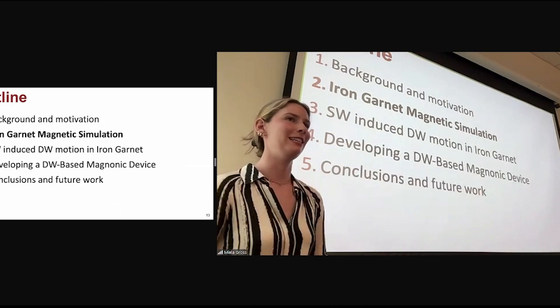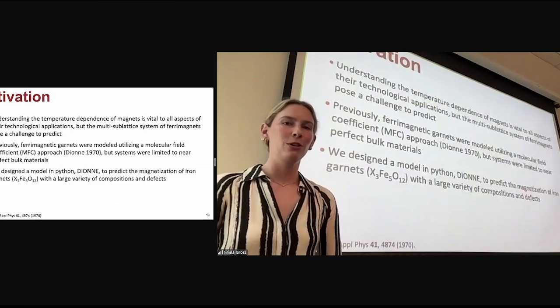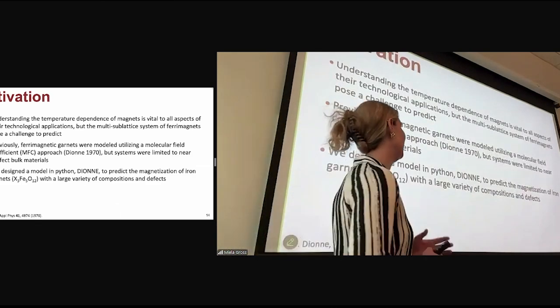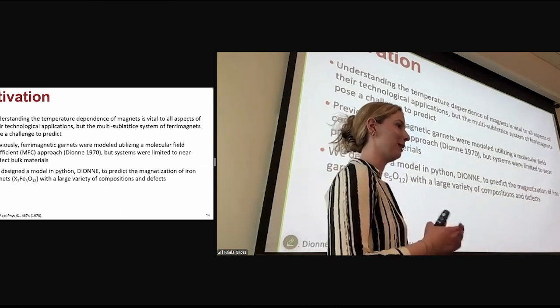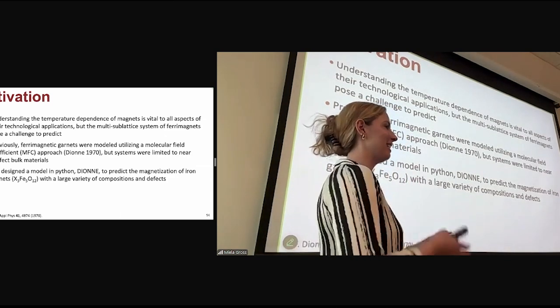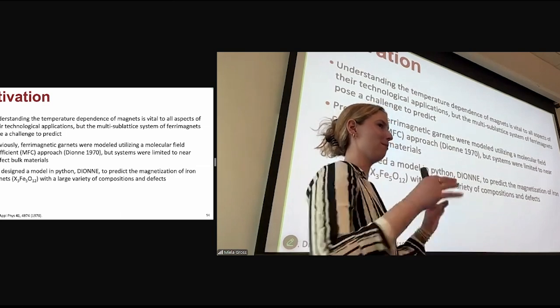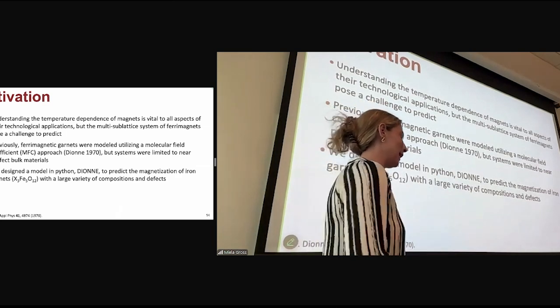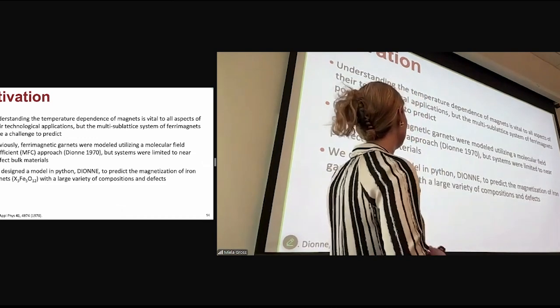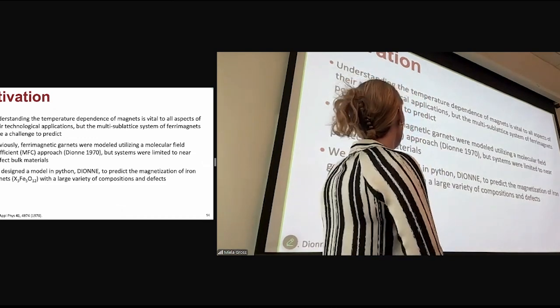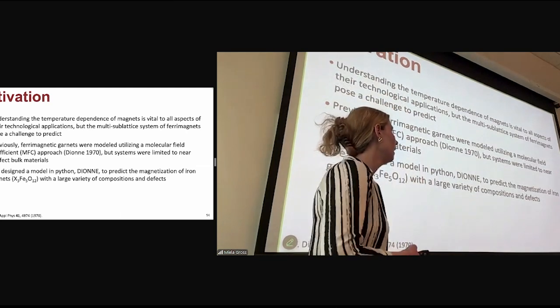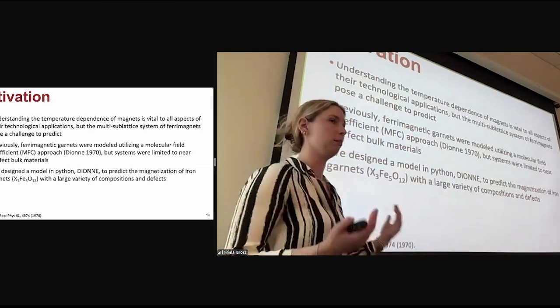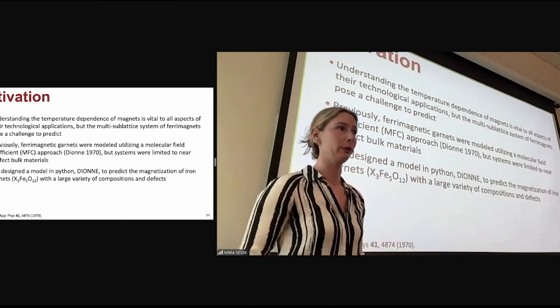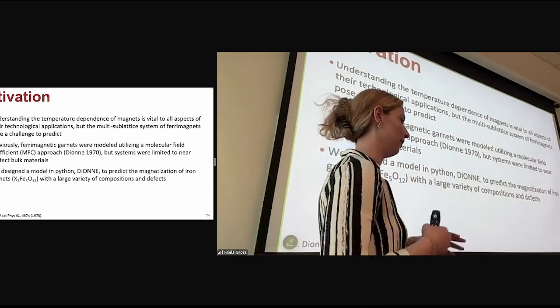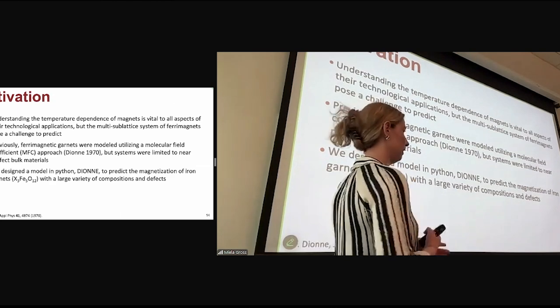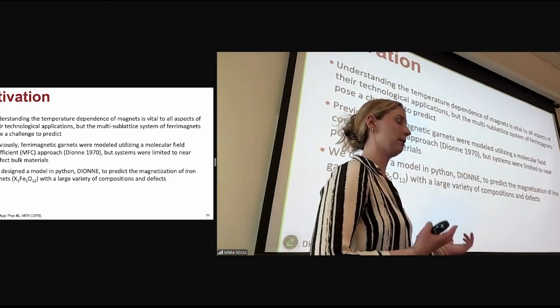So now I'm going to dive into my little simulation. So we developed this model because predicting the moment of ferrimagnets as a function of temperature becomes very challenging, as each of the sublattices causes the overall net moment to vary non-monotonically. So previously in 1970, Dionne developed a molecular field coefficient approach, but his systems were limited to near perfect bulk materials. And in the 70s, that's what you were working with. But here we look at thin film epitaxial growths where off stoichiometries could be stabilized.